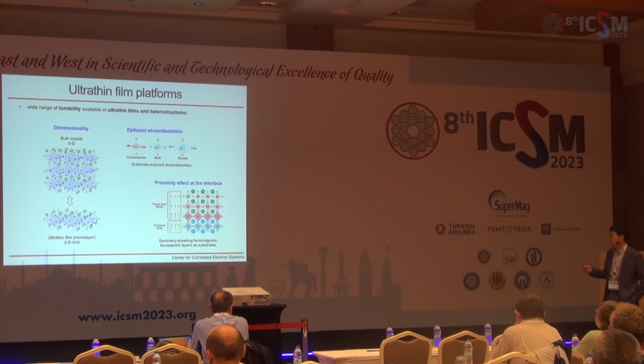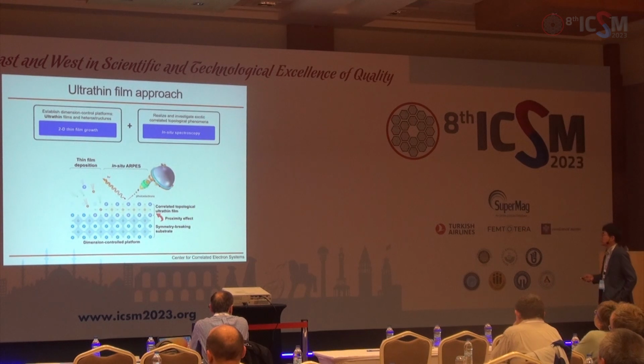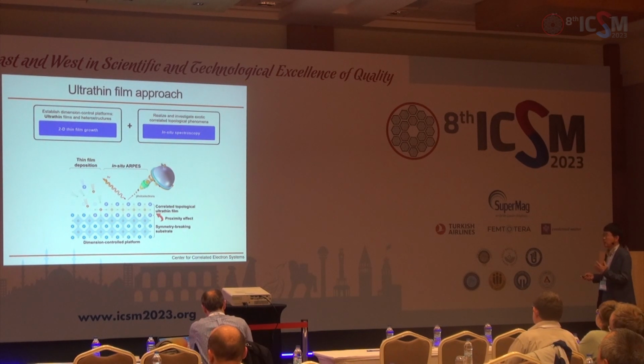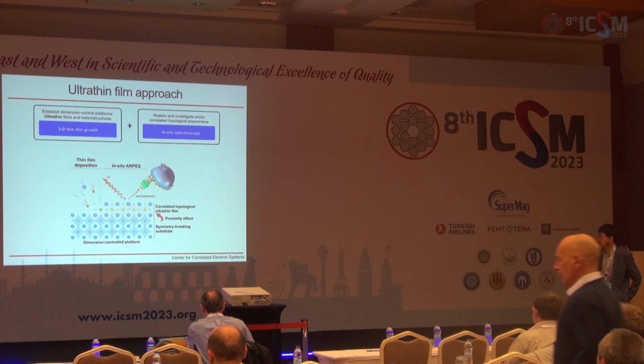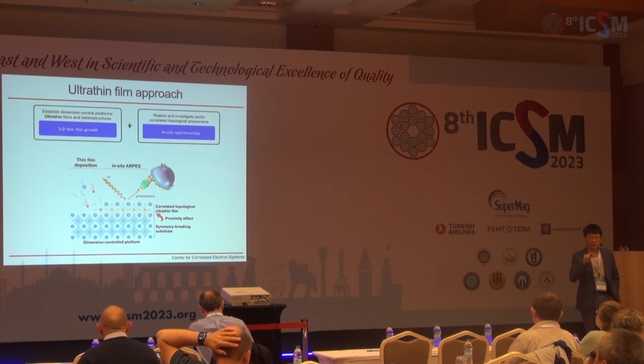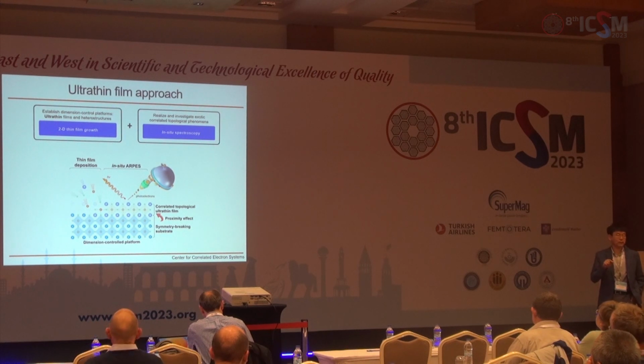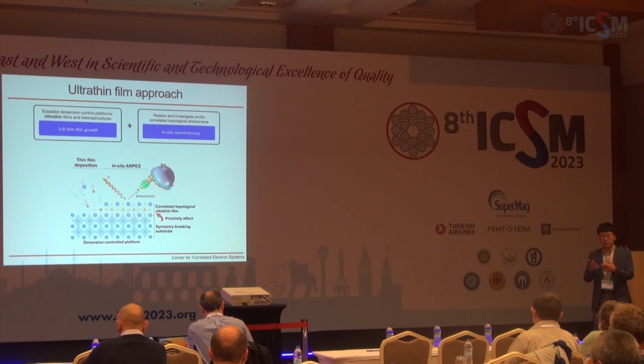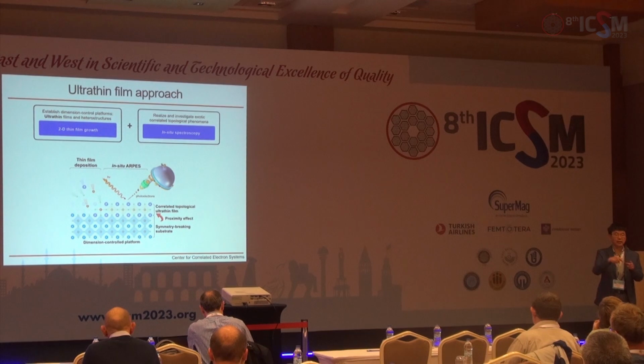So that's basically ideal. And what I do is using this 2D thin film growth and combine it with in-situ spectroscopy, that is ARPES, and study the electronic structures. Why do we have to do ARPES? If you think about these thin films of atomic layers, transport measurement is extremely difficult. I will show you later that one of the reasons is that if you were to measure, for example, electrical conductivity, there are step edges, and these